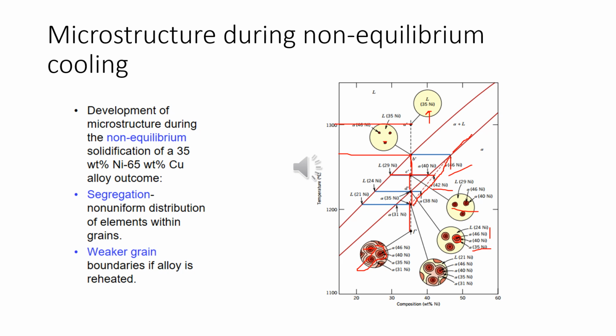Furthermore, this melting, alloy coring, may be eliminated by homogenization heat treatment carried out at a temperature below the solidus point for a particular alloy composition. During this process, atomic diffusion occurs, which produces compositionally homogeneous grains.